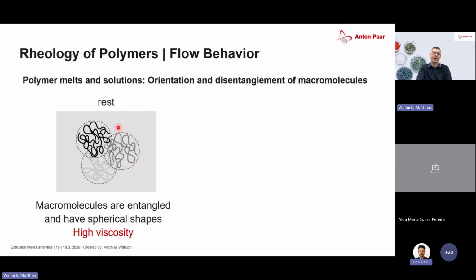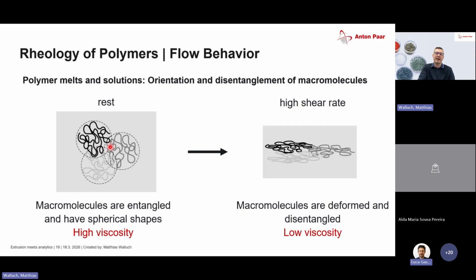Why is that? Because of the inner structure of a polymer. Polymers have chains and side chains, and they interact with each other. So every molecule is in the beginning at rest, they interact with each other, and then the viscosity is high. And if I apply a shear rate, I start to move these polymers, and the inner chains start to deform and then start to slide on each other. And then the resistance goes down, and we have disentanglements, and the viscosity is getting lower and lower.